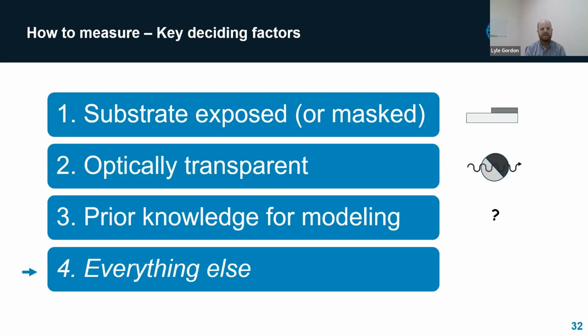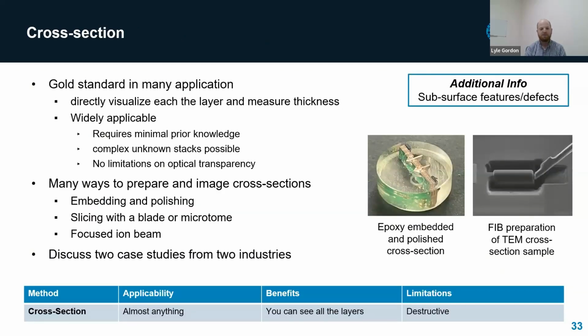So what do you do in other cases where you don't have good optical transparency, you can't expose the substrate, maybe you don't want to destroy the sample, or you didn't make it, or it's buried? And so there's some nice applications where, how do you figure this out? And the answer that we typically use is kind of the gold standard. You just cut the thing in half and directly measure the thickness that you see once you've made a cross section. And this can be done in a number of ways.